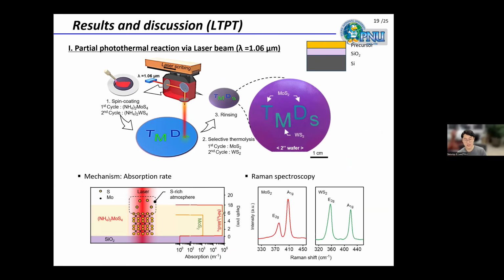Both questions are really harsh for me. First question, due to the time limitation, I didn't put thickness information of the MoS2. My target is to synthesize a monolayer of MoS2 using this system. But as you can expect, the laser ablation process is really harsh, so I cannot get mono and bilayer MoS2 film. Partially I can get that kind of thin MoS2, but for a film type of MoS2, the minimum thickness is 3 layers.